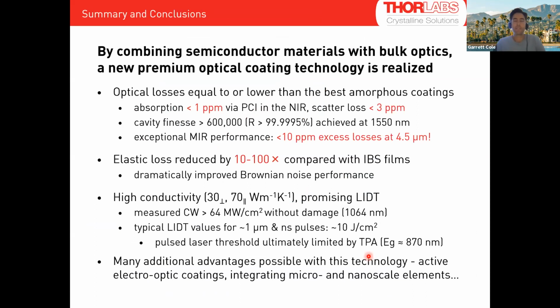This is the final slide here. So, in summary, using this interesting combination of semiconductor materials and microfabrication techniques with bulk optics, we've realized a new premium optical coating technology, with high performance in terms of low absorption, low scatter, and so on in the near IR. And now, for the first time, we're pushing it into the mid IR, with very low Brownian noise, which you now hopefully understand. Feel free to ask me questions about that. It means you can make the world's most precise, most stable, quietest interferometers, whatever you want to say. These materials have relatively high thermal conductivity, high CW damage threshold, and so on.